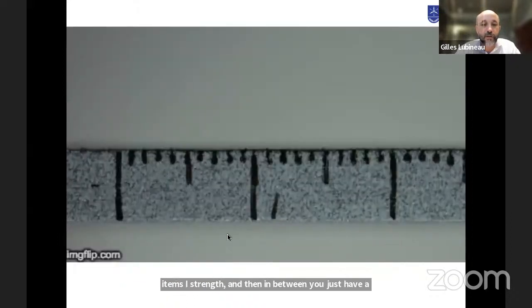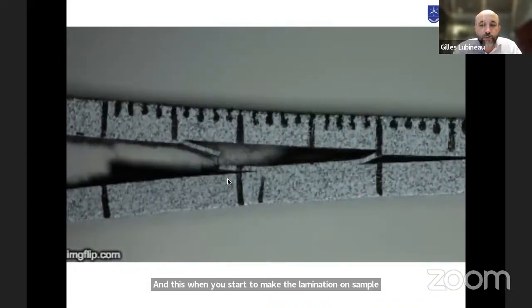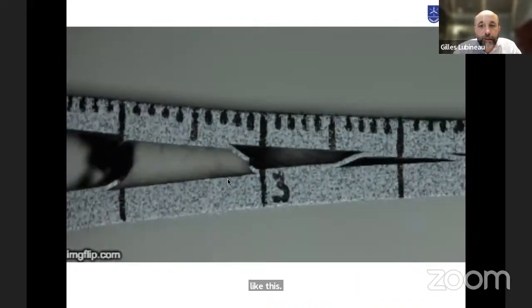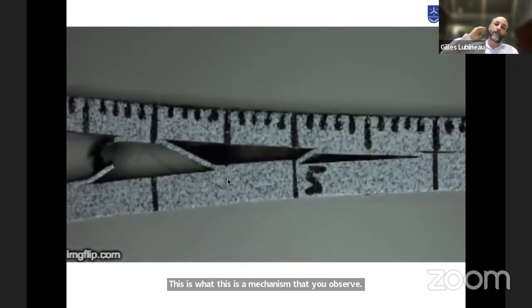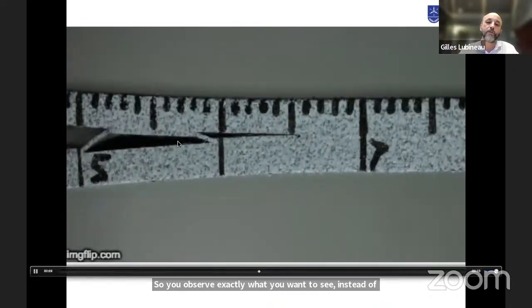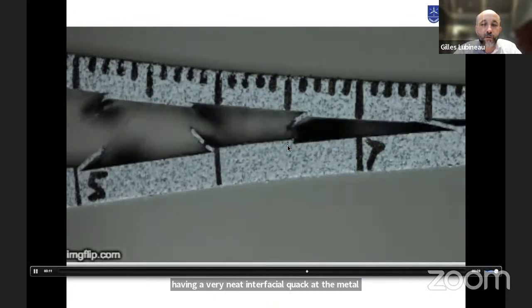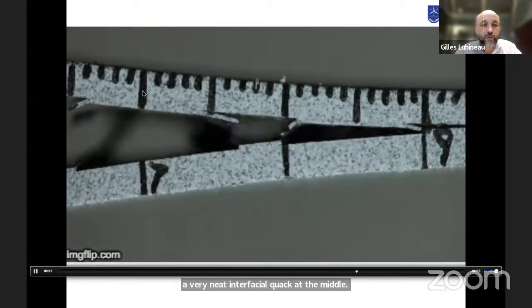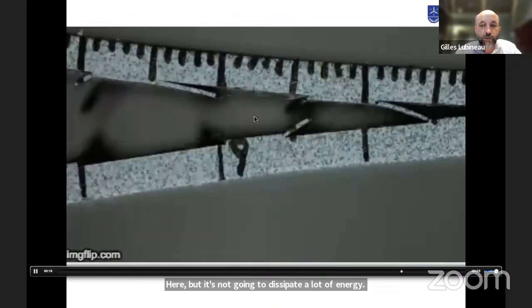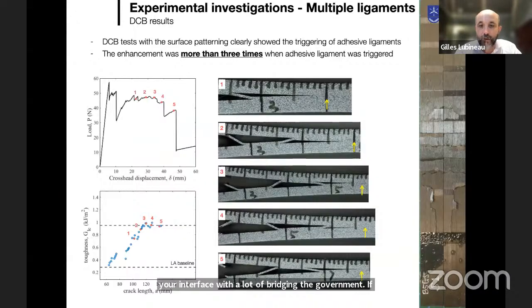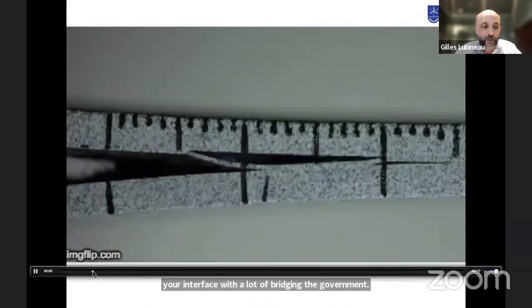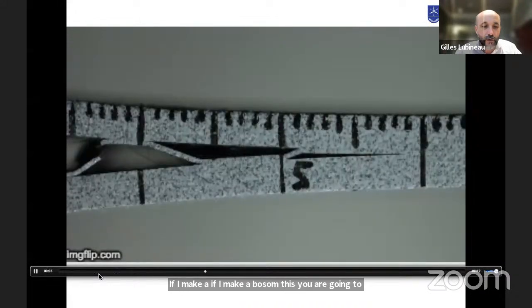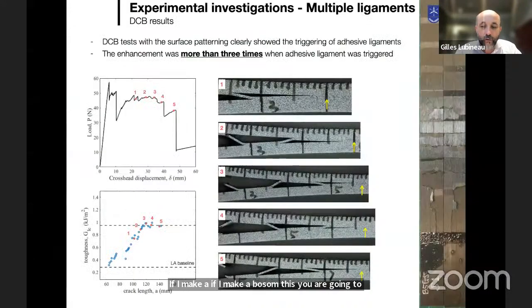And when you start to make delamination on a sample like this, this is the mechanism that you observe. So you observe exactly what you want to see. Instead of having a very neat interfacial crack at the middle here that is not going to dissipate a lot of energy, here you start to introduce a lot of fragmentation of your interface with a lot of bridging ligaments. If I pause on this, you are going to introduce a lot of bridging ligaments here that will bridge the top substrate to the bottom substrate.